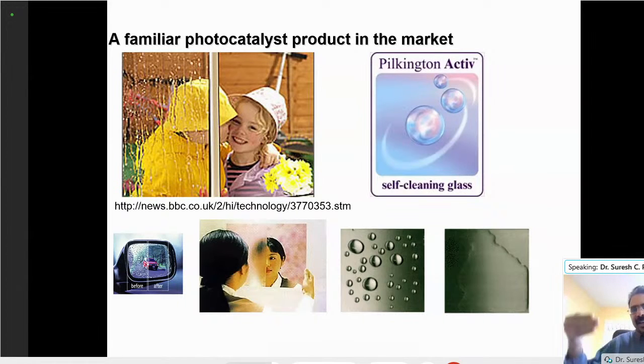But if you use a photocatalytic material, there wouldn't be any droplets. The water droplet will form a thin film over the glass. So you wouldn't even notice that. So that is what's happening with the photocatalytic glass. If you use a photocatalytic glass in your bathroom, after the hot shower, you can easily see in the glass. There wouldn't be any mist. Whatever mist formed on the surface will form as a thin film.